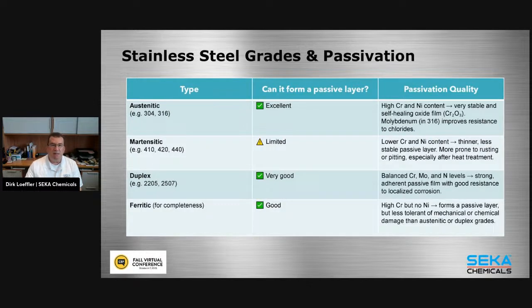So we've talked about stainless steel. Can it form a passive layer? Yes, technically all these steels can form a passive layer. The question is, what quality is this passive layer, and how much does it protect our steel? Austenitic steels provide an excellent environment to form a passive layer. We have a high chromium and nickel content that provides a very stable and self-healing oxide film. And if we add molybdenum, generally in 316, that can further improve resistance to chlorides. And then we also have the L grades, as we call them, low carbon, that will further increase the resistance against chlorides. You find those commonly in dairies.